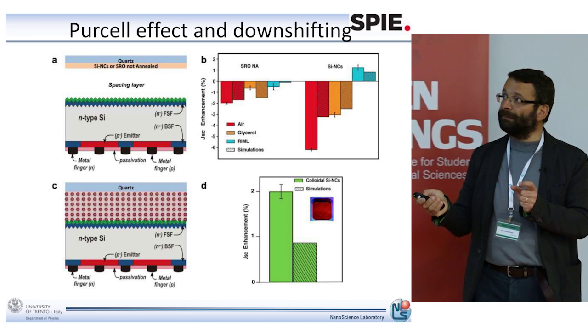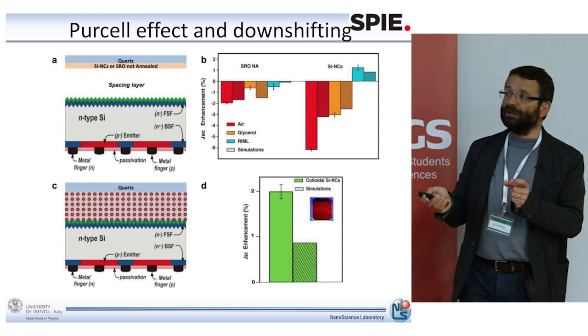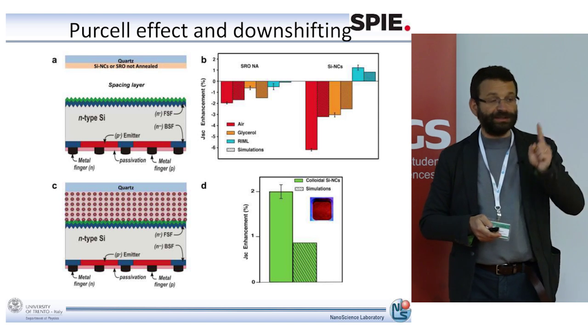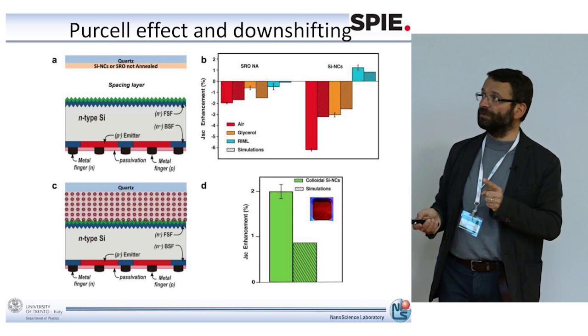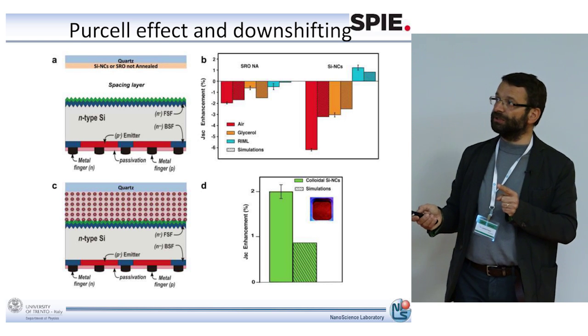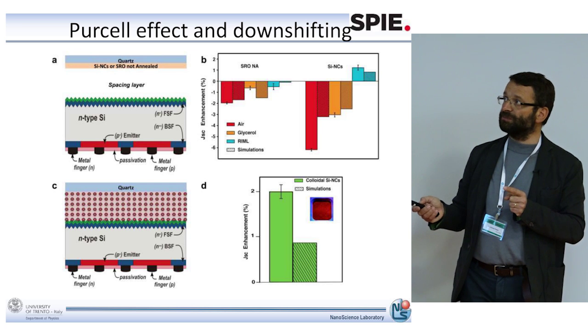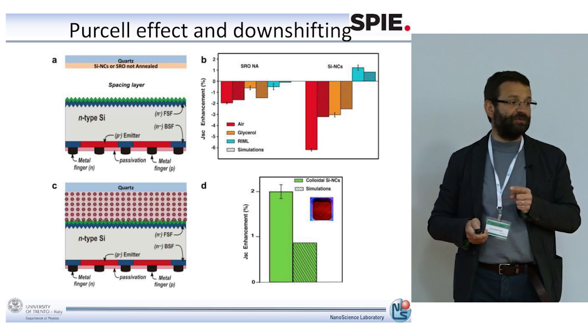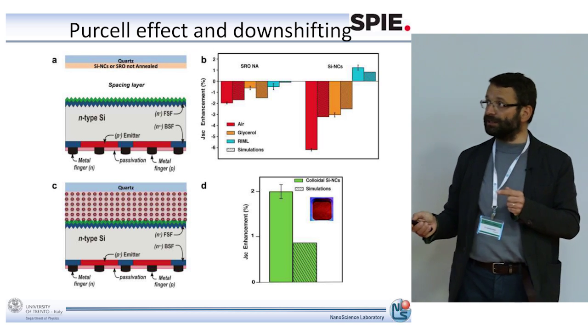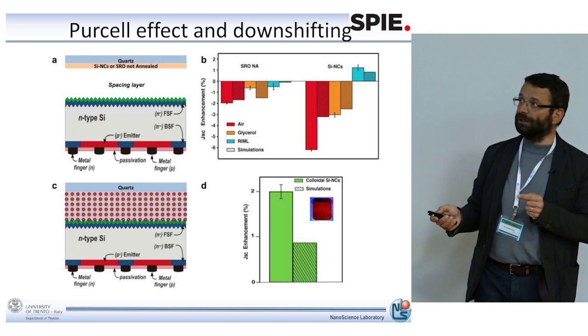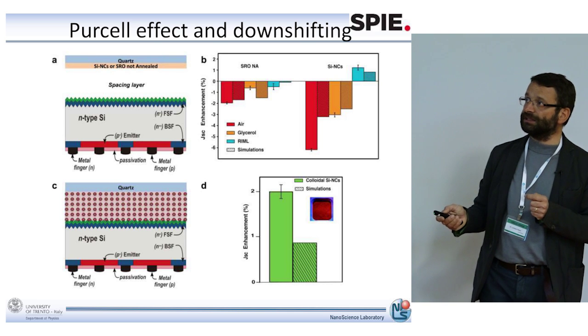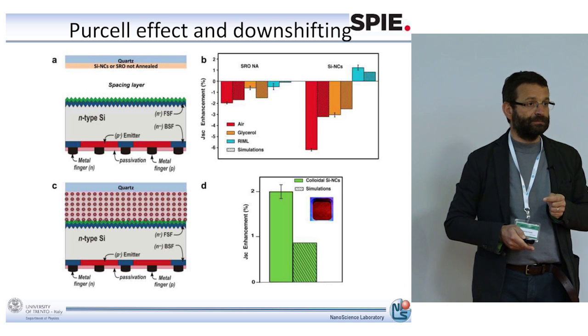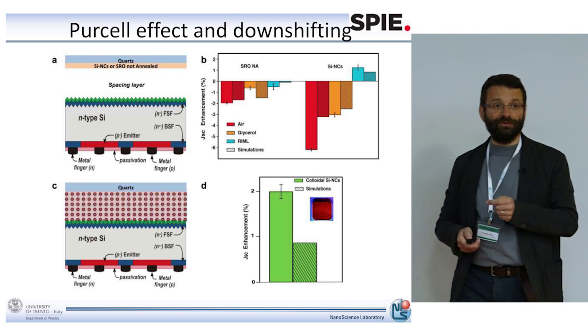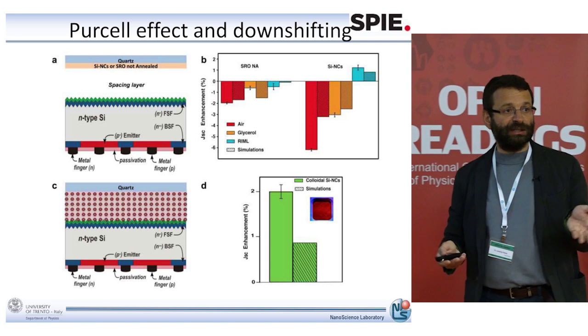And then we fill the gap between the nanocrystals and the cell with different liquids. And here is a very important physical point. What we observe is that the short circuit enhancement for the nanocrystals is larger than 1 only in a very specific case. This is the case when we put on the spacing layer a liquid that has a refractive index larger than that of the nanocrystals. And the reason for that is simply the standard Purcell effect.